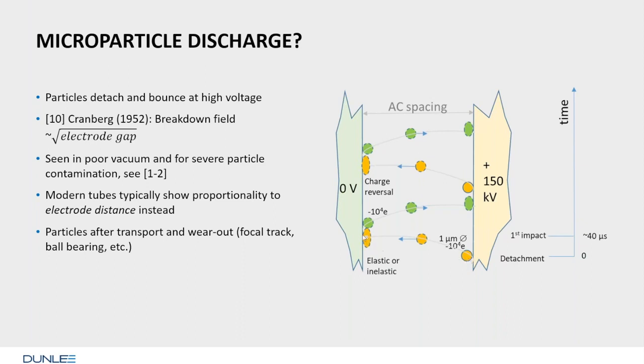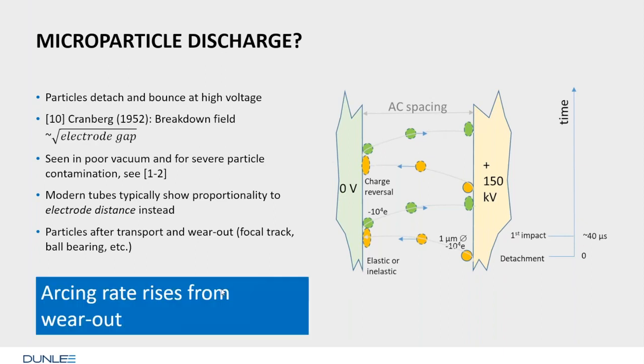It's pulled off, moves to the other side, returns and swaps its charge, and bounces back to the anode, and it gains energy. And Mr. Cranberg in 52 said, well, if the particle hits a surface so hard that the surface is damaged and evaporates, then we have what we're looking for, plasma, or vapor turning into plasma. So this theory is a little bit tricky. I don't want to go into more details, but at least some particles, if they are large enough, can create arcing with some kind of this process. So the arcing rate in tubes may rise from wear out of ball bearings, of anodes, and of other stuff.